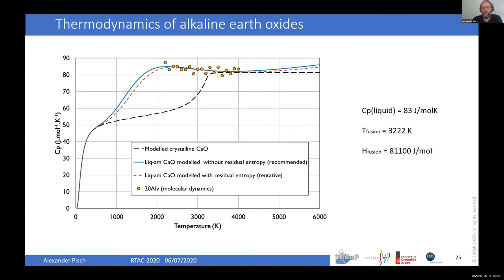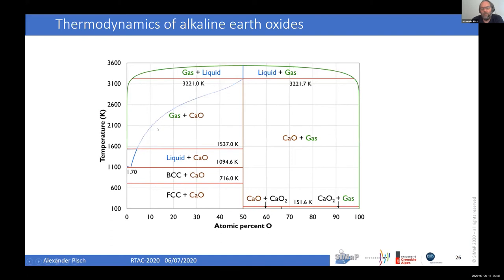And the last but not least, the heat of fusion is around 81 kilojoules per mole, which means that you have an entropy of fusion of 25 joules per mole per Kelvin, which is also an estimation done in the Gurvich compilation. And we think this is the right one. So using now this new CaO, we did the CALPHAD assessment of the calcium-oxygen system.